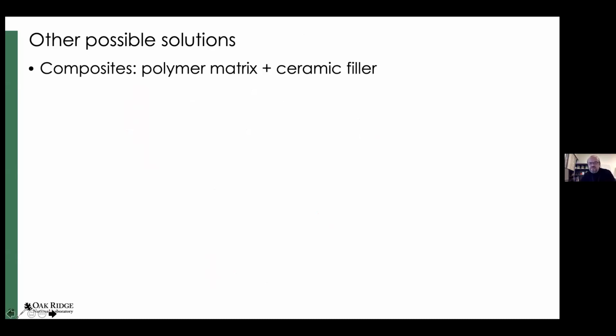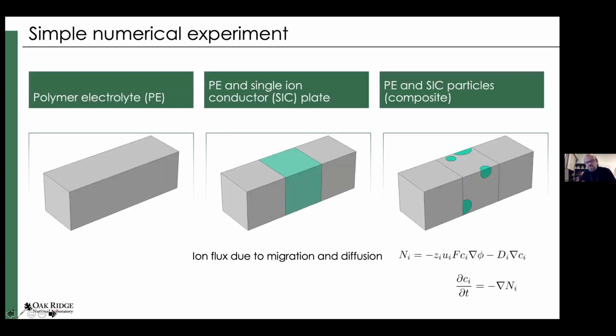So other possible solutions that people looked into are composite electrolytes, where you mix a polymer matrix with a ceramic filler. Just like in any other composite engineering, you impart strength by the ceramic filler, and the polymer matrix is supposed to provide ductility and play a role in the ion transport. However, if you do that with a very dry polymer, addition of the particles of the single ion conductor actually does more harm than good.